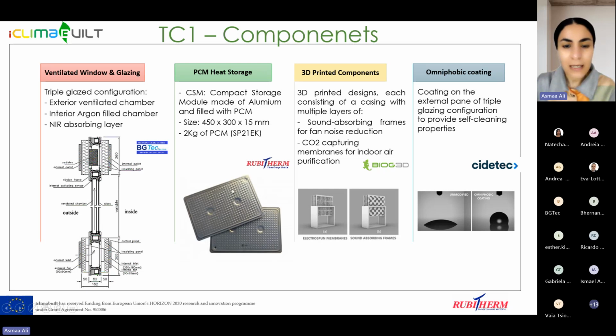aluminum casing, as you see here in this picture, with dimensions of 450 by 300 by 15 millimeters, and it can be filled with many different PCMs. For a standard filling of a PCM of SP21, which is a salt hydrate based PCM with a melting point of 21, it can be filled with 2 kilograms.